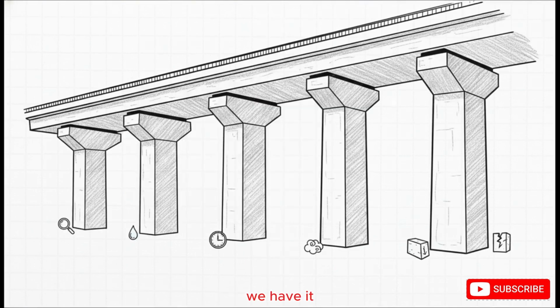And there we have it. Let's step back and look at the complete picture for a second. The entire journey from a microscopic gray powder to a towering, indestructible stone is governed completely by these 6 pillars. The rapid hydration unlocked by fineness, the perfect paste born from standard consistency, the crucial construction window defined by setting time, the lifelong stability ensured by soundness, the ultimate load-bearing power proven by compressive strength, and the critical resistance to cracking mapped out by splitting tensile strength.